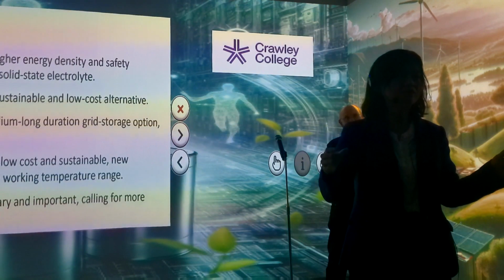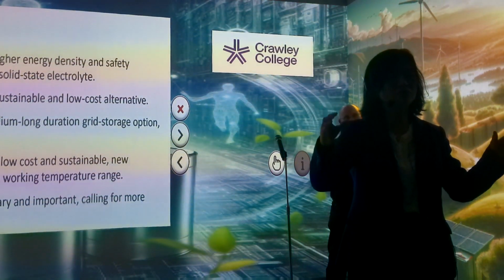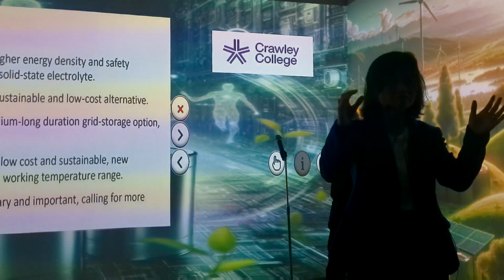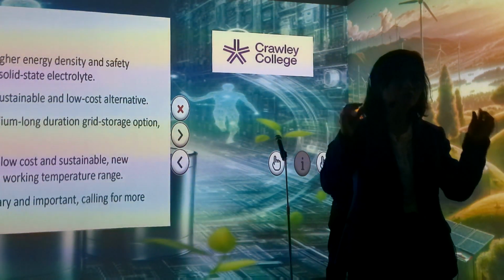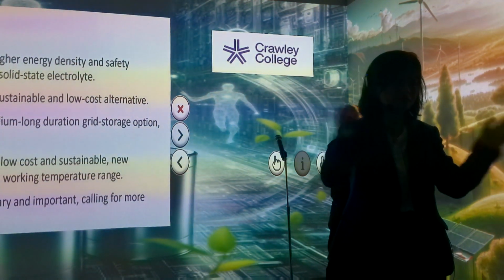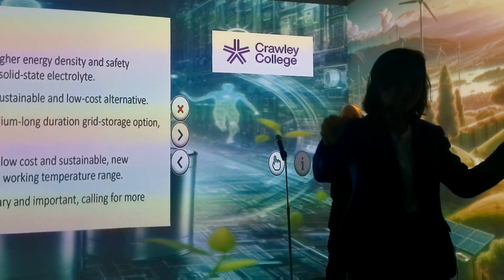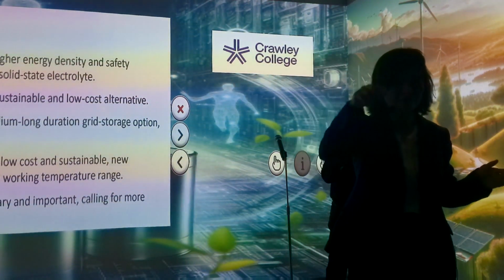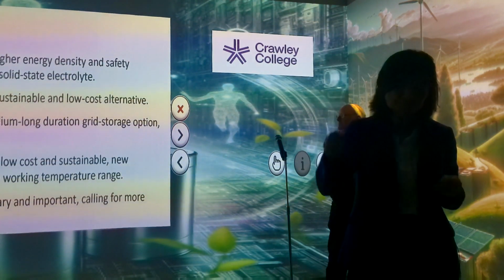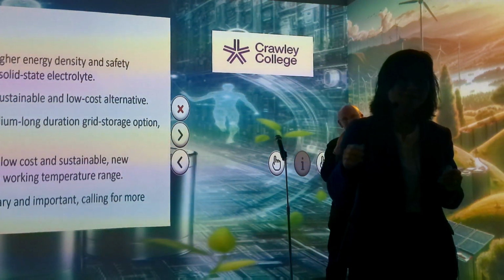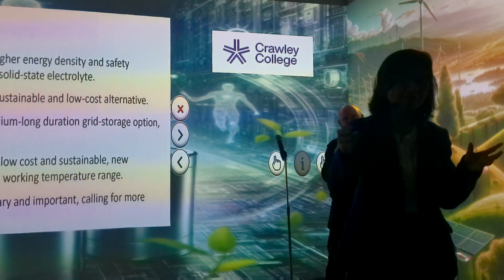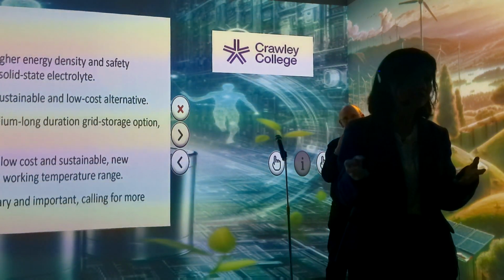So temperature increase plus oxygen release will cause, if these are not properly managed, if you don't manage the temperature very well, if you don't limit your battery to only operate at a certain voltage window and only charge it below 100 SOC, state of charge, then those things will happen, and then you will have a fire.